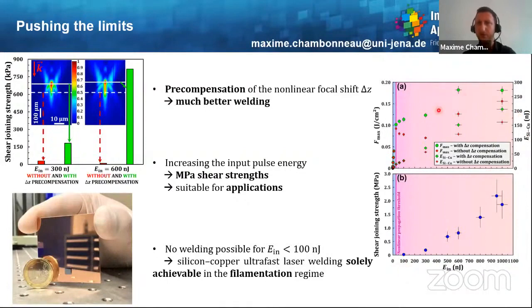Besides, here on the top, one can see the evolution of the maximum fluence reaching the interface, as well as the energy deposited at this interface, or the energy reaching this interface, as a function of the input pulse energy. And one can here again see that precompensating the nonlinear focal shift leads to enhanced energy deposition.